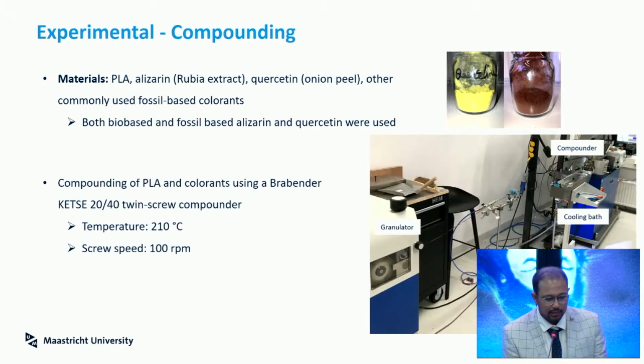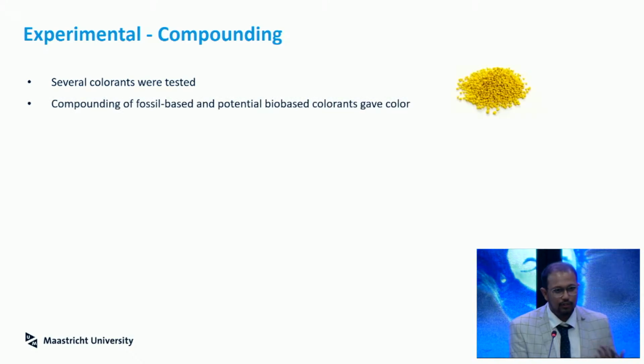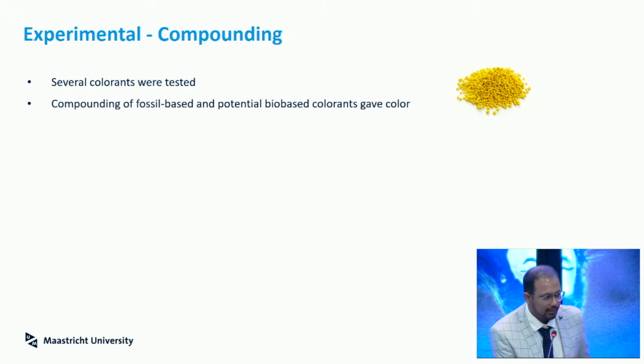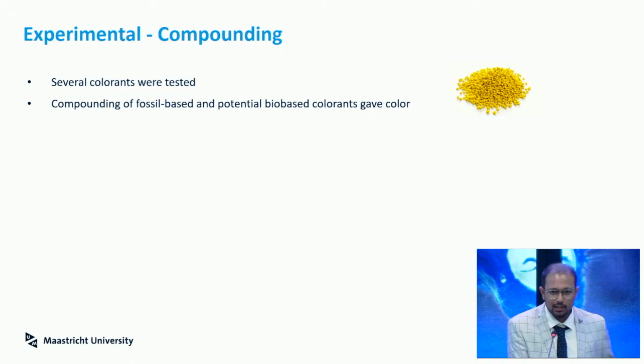I did this using a twin screw compounder, where I was just putting in the polymer material and the colorant, and then mixing them together to make small strands, which were then used to spin yarn. What I observed during testing of these several colorants was that for fossil-based and potentially bio-based materials, for example alizarin and quercetin made directly from oil, it was working fine. I had a really nice bright color.